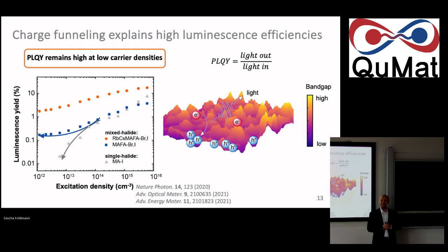Great. If you have traps, isn't it a problem for PV performance? Yeah. So you want reduction as well as the capturing. You are fine if these are shallow enough traps that they don't completely kill your excited state over time. And of course, we extract here vertically, so the diffusion length is still okay even then. This effect for the solar panel, for example, only works, it's more subtle than this, of course, only when there's a difference between your trap density for electrons and holes.